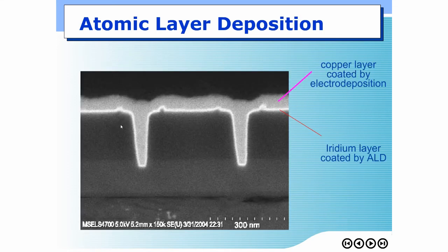Just like in this picture, this bright line is the layer formed by ALD. You can see that even though the scale is nanometers, the width of this trench is really small. If you use other techniques, you might not get the penetration of the precursor down to this deep trench, but ALD you can. The other thing that you should notice is that the thickness of the film is quite uniform all the way, totally uniform. So this is a good advantage of ALD.